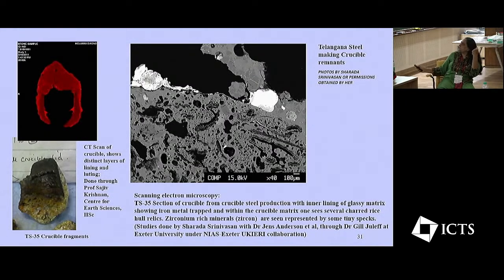And other scholars have also found the formation of mullite networks and so on. Another interesting aspect is that I found quite a few specks of zirconium-rich materials through the fabric. Of course, we know that quartz was being deliberately added because quartz is silica-rich and quite refractory. But this finding of zircon minerals in tiny specks is because some of the sands in Andhra Pradesh apparently are rich in zirconium minerals. So that could have also contributed to improving the refractory properties, because zirconium is also one of the highly refractory materials which are used in modern conditions. So even in the traditional setting, some of these were being used. Of course, they would have sought out the materials that worked for them, not knowing exactly what they were.